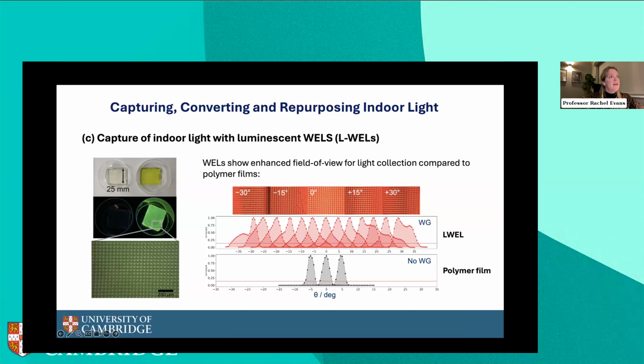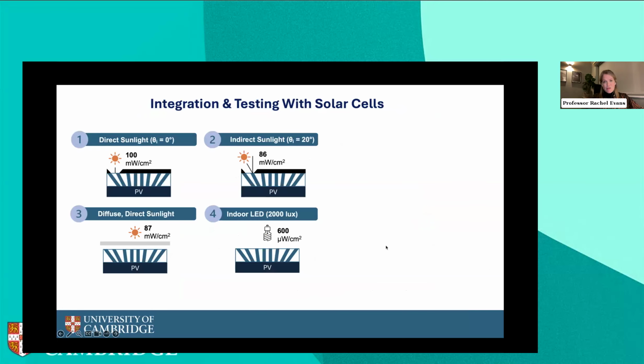So then finally, the next step is to integrate our WELs and test them with a solar cell and see how it affects the performance. In these proof of concept experiments, we place either the WEL or an off-pattern film on top of the solar cell, and then we measure the cell performance under different incident light conditions. So the first one is direct sunlight at 0 degrees. The second is indirect sunlight at an angle of 20 degrees. Then we use diffuse direct sunlight, and then finally an indoor LED. And hopefully you can see that these all have quite different incident powers.